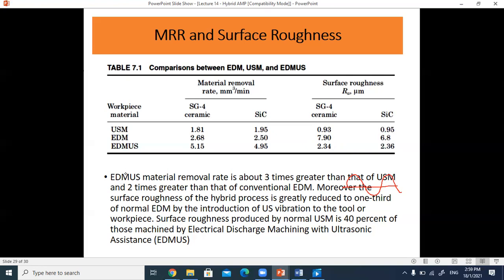So the ultrasonic EDM process material removal rate is about 3 times greater than that of USM, and 2 times greater than the conventional EDM process. Moreover, the surface roughness of the hybrid process is greatly reduced to 1/3 of the normal EDM process. So there's an improvement in surface roughness between EDM and ultrasonic assisted EDM. The surface roughness produced by normal USM is 40% of that machined by electrical discharge machining with ultrasonic assistance. However, USM will give a much better surface finish compared to even EDMUS.